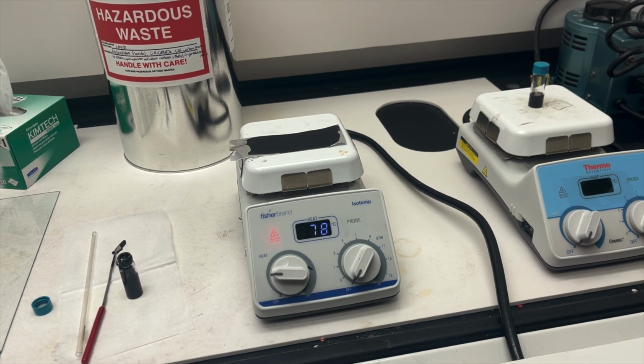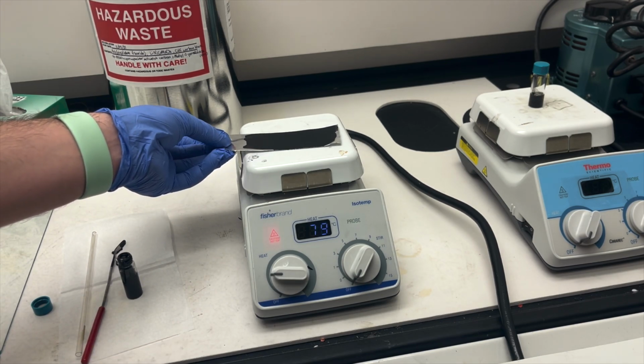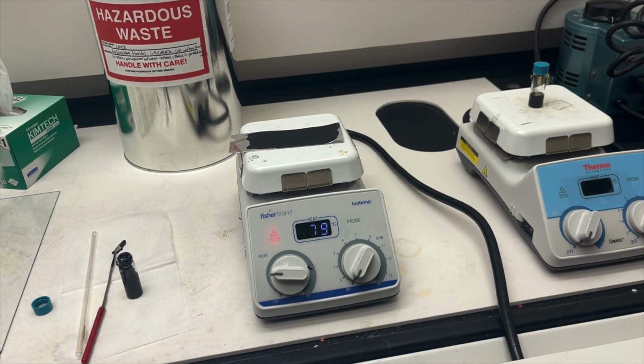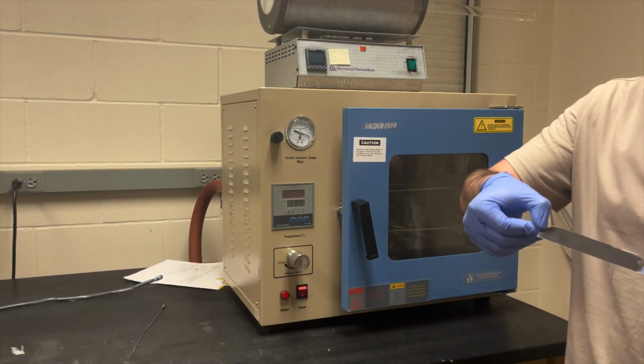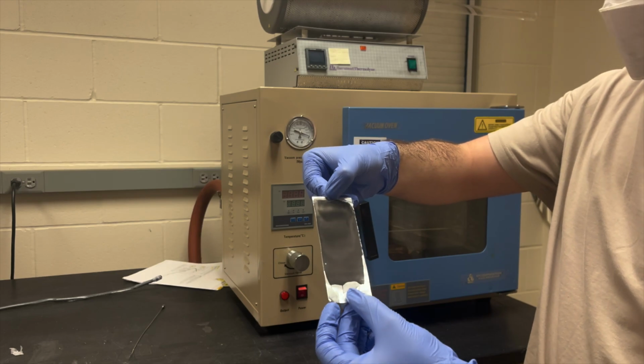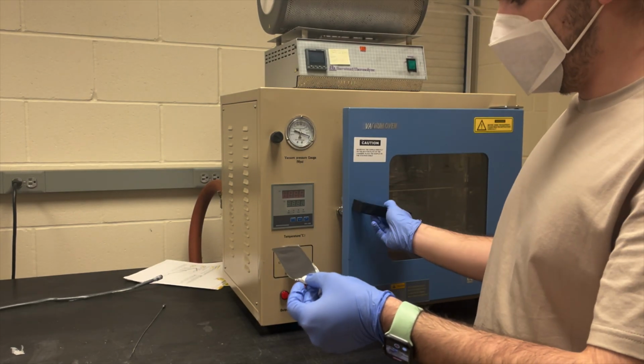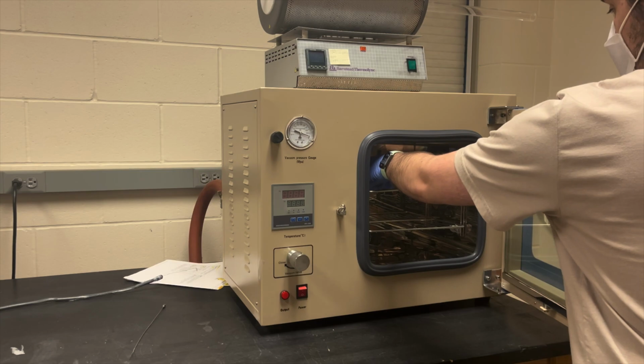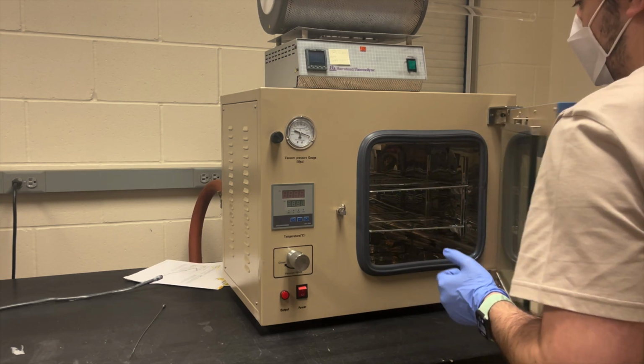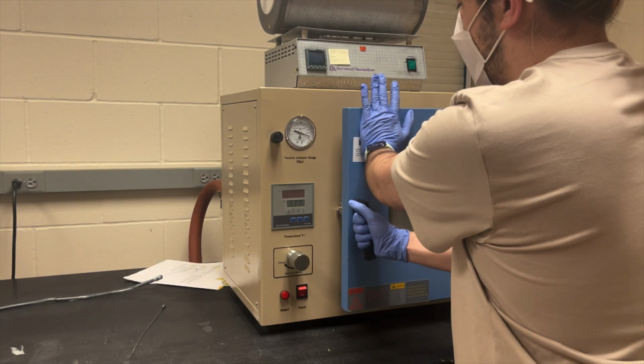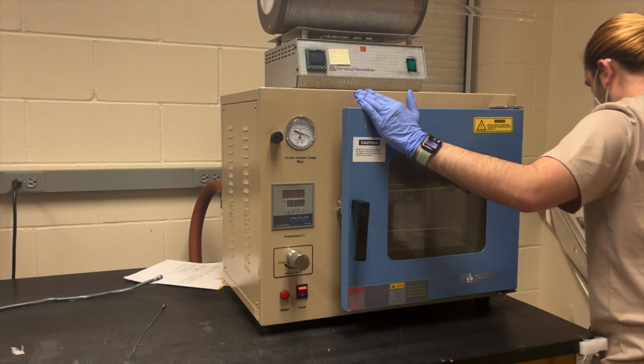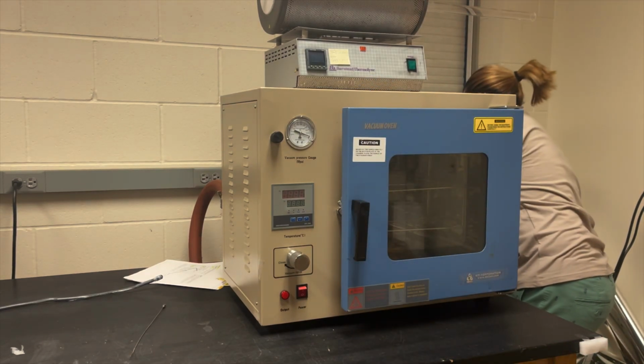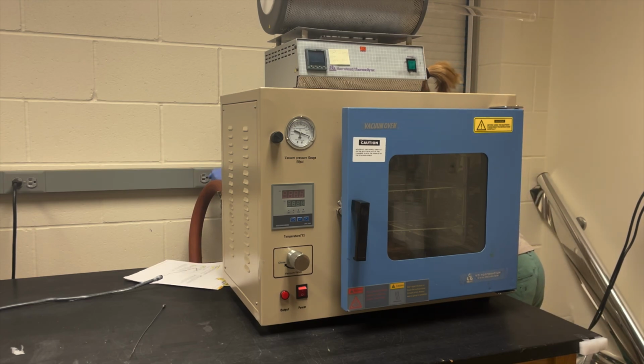We will leave the casted foil on the hot plate until we see that all or most of the NMP has evaporated, at which point we will transfer the foil from the hot plate to the vacuum oven. Taking our casted electrode and placing it into the vacuum oven, we will begin the process of dropping the pressure. Here, I'm plugging in the pump behind the oven, which begins to evacuate the chamber.